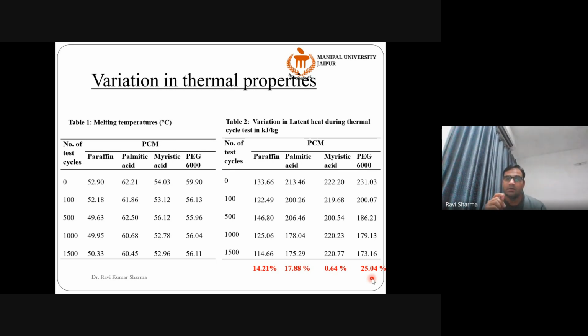But being an honest and intelligent real application engineer, you have to look at the trend. I want all of you to look at this trend. What is happening after 100 cycles? Is the value decreasing or increasing? You see, after 100 cycles, in the case of paraffin, it decreased, but after 500 it increased. After 1000 it decreased, at 1500 decreased. In the case of palmitic, decreased, increased, decreased, decreased. In the case of myristic acid, decreased, decreased, increased all of a sudden, and then increased. PEG decreased, decreased, decreased, decreased. So PEG has shown a very beautiful pattern.